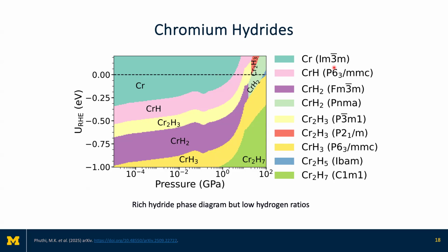Coming back to the superconductor application, one thing you didn't comment on is the role of dynamical stability of these phases. You can calculate that at the quasi-harmonic or harmonic approximation. And we know experimentally that you can stabilize these superconducting phases well below the pressures at which they are dynamically unstable, because of various anharmonic effects.